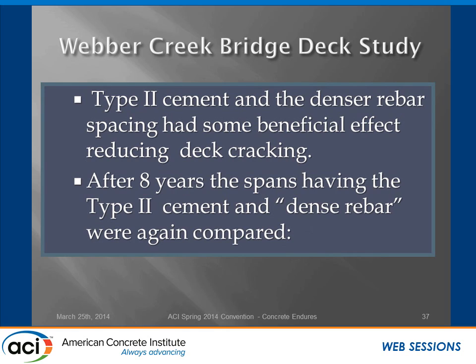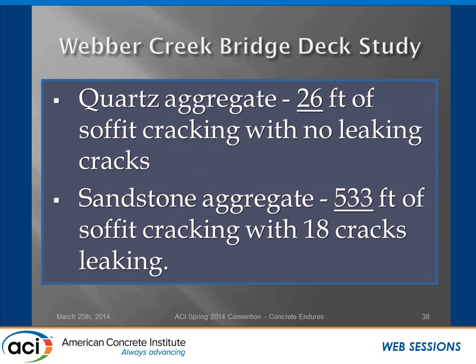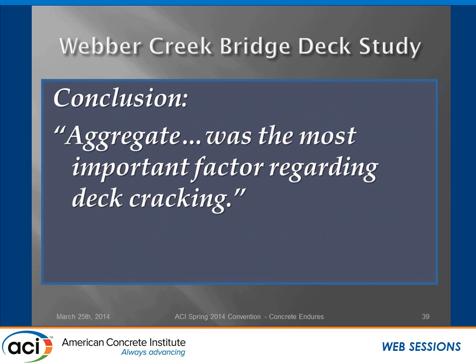So what was discovered? Type 2 cement and the denser rebar spacing did have some impact on the crack performance. After 8 years, the spans having the type 2 cement and the denser rebar were again compared. This is what we got. Concrete with the quartz aggregate had only 26 feet of soffit cracking. We're down under the deck looking at it, so we don't have to dodge cars. And the sandstone aggregate had 533 linear feet of cracks, and 18 of those cracks were leaking. None of them were leaking on the quartz aggregate. So that indicates how wide the crack became. The reporter's conclusion was that aggregate was the most important factor regarding deck cracking that was under our control at the time.